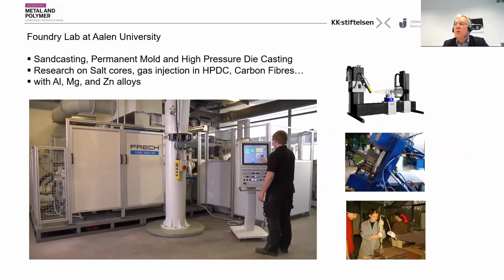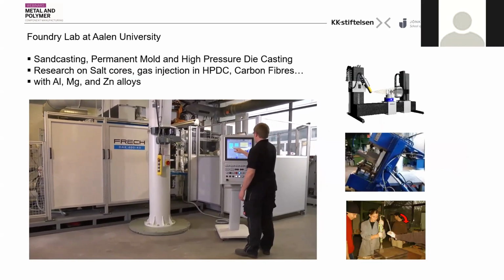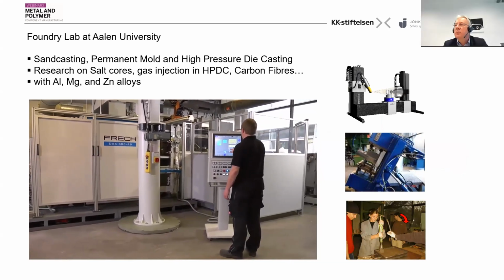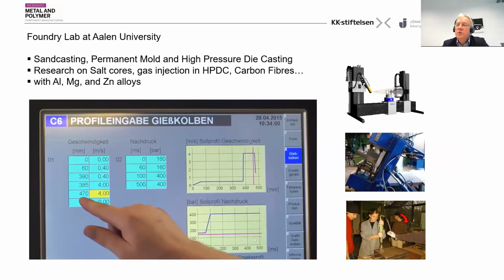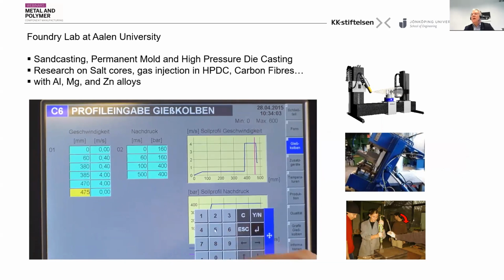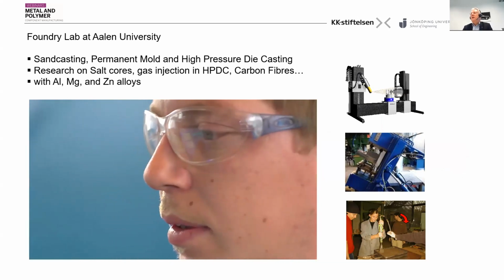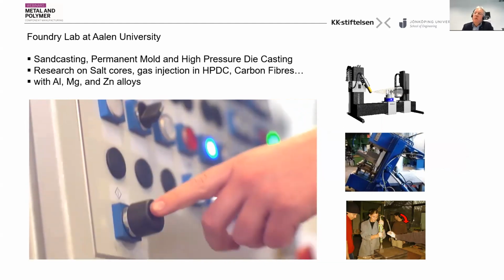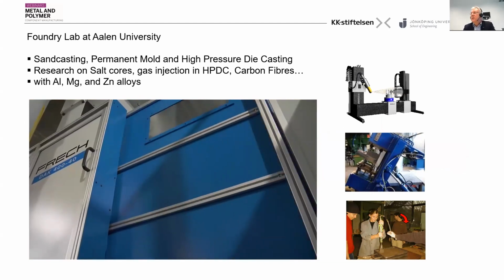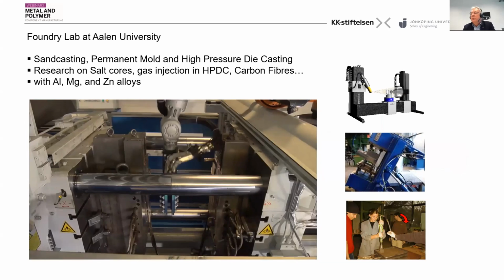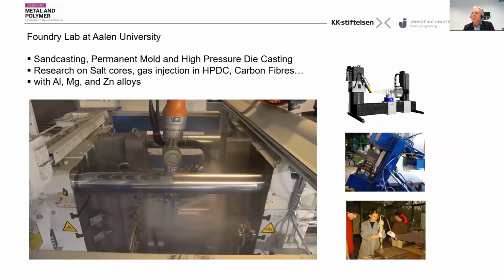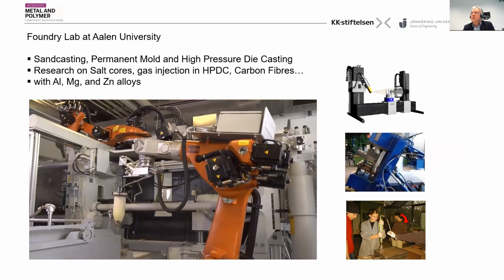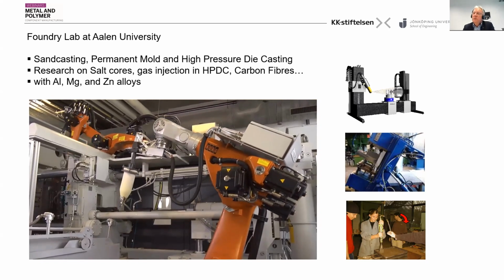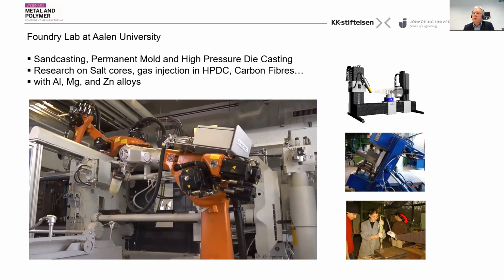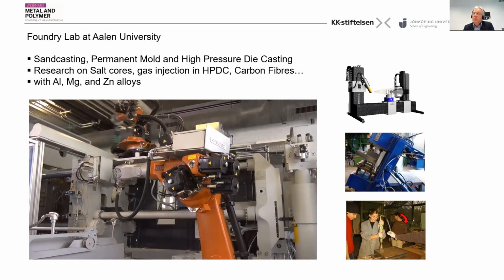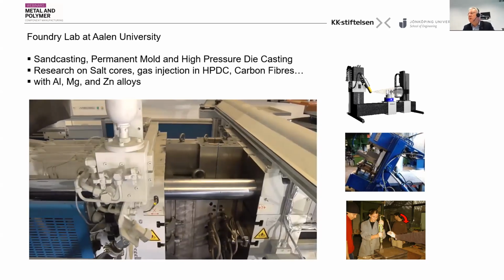Okay, what are we doing in our lab? We have a very nice lab with 3 high pressure die casting machines. We can do sand casting, permanent mold, and we do research on salt cores in high pressure die casting, gas injection in high pressure die casting, and carbon fibers, and we can run aluminum, magnesium, and zinc alloys. And here you see our middle machine, 400 tons, doors closed. We have automatic spraying. This is the parting agent Anders was talking about. We have a new system to dose the metal into the shot chamber. In this case it is aluminum, but we can also use magnesium and all that stuff.